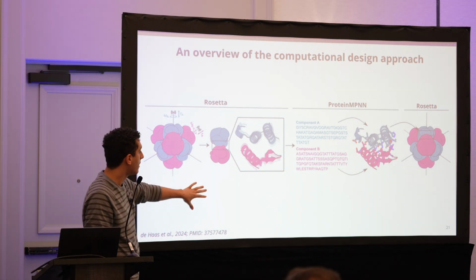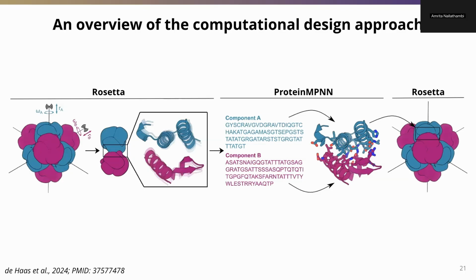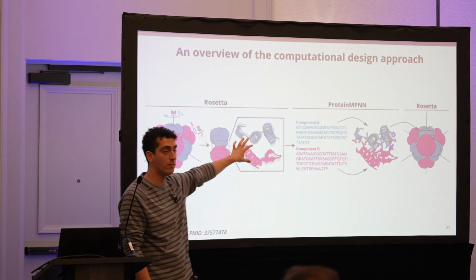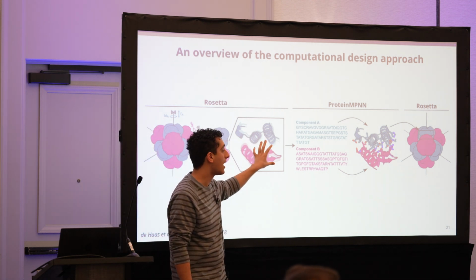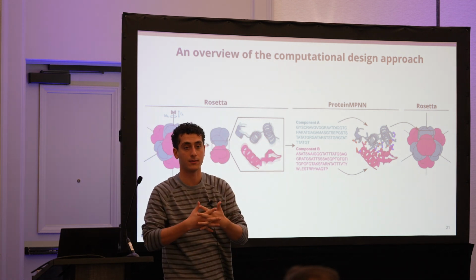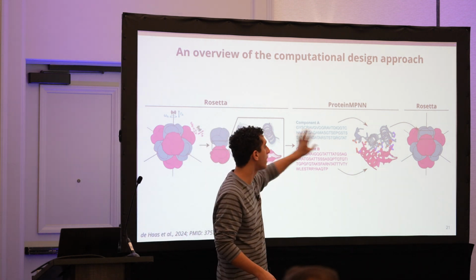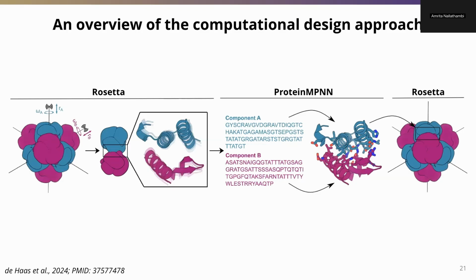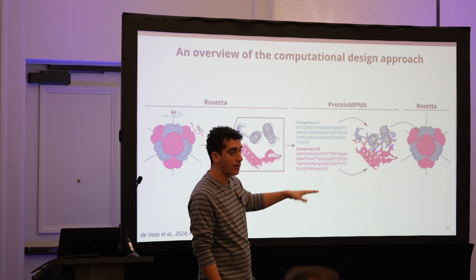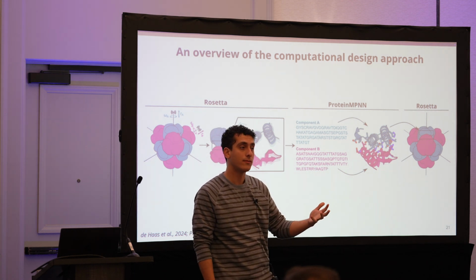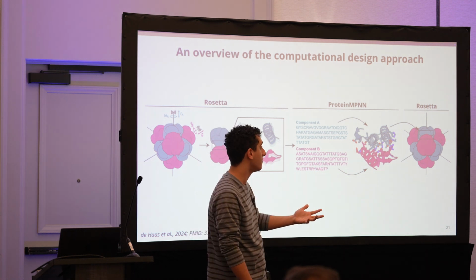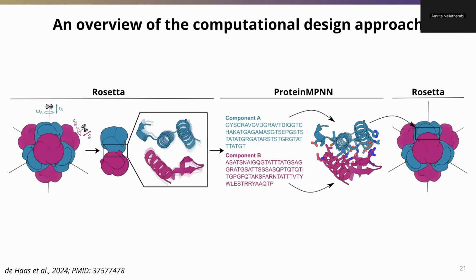When you do that, you then take your interface, and you've decided that these are the pieces from that given architecture that dock, that form that we're interested in, and we want to design that specifically to actually self-assemble. This is where ProteinMPNN comes in, and you can say, okay, let's see if we can actually get a good interface using ProteinMPNN. ProteinMPNN, like I said, tends to do more polar interfaces, which we've seen seems to be better, ideally, than the hydrophobics, so that's good.